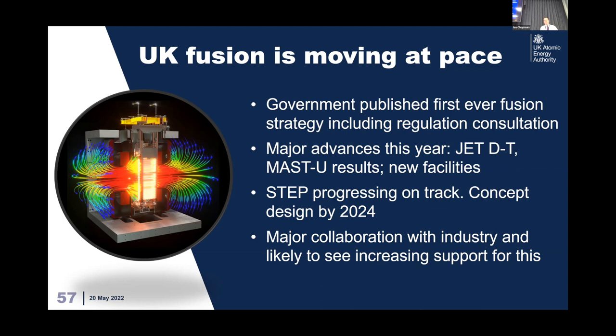So for those outside the room, the questions were around skills pipeline and tritium storage and how difficult that problem is. So on tritium, first of all, the storage of tritium is very well understood using metal hydrides. It just forms very strong bonds, and you heat it up and it releases. The problem with tritium is much more around the permeation through materials, but there are anti-permeation barriers that you can use with palladium membranes, and we're looking at graphene and other things. That is a problem, but it's not on the top of the list of technical problems.